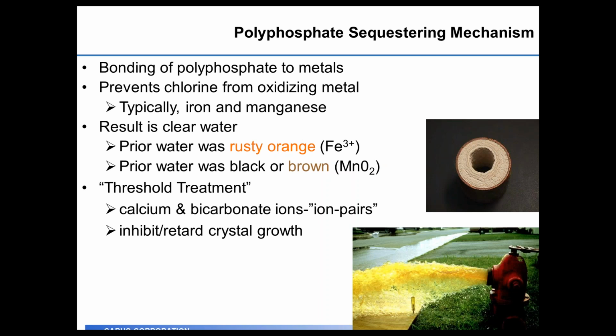Polyphosphates are known as the sequestering agent in the distribution system. They are the bonding of that polyphosphate to the metals in your water. What they do is they prevent chlorine, which also acts as an oxidizing agent in addition to being your disinfectant in your distribution system, from oxidizing the metals. Typically what happens is chlorine will oxidize the iron and manganese in your water and precipitate it out of solution. If you have iron, the water will become rusty orange as it gets oxidized, and if you have manganese in your water, it will become black to brown depending on the concentration.